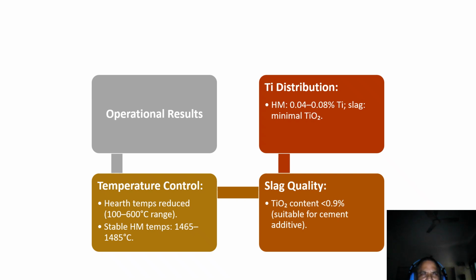This method helps control hearth temperature, dropping it by 100 to 600 degrees centigrade while keeping hot metal temperature stable between 1465 and 1485 degrees centigrade. The slag still meets cement industry specification with less than 0.9% TiO2. That means better production with no compromise.